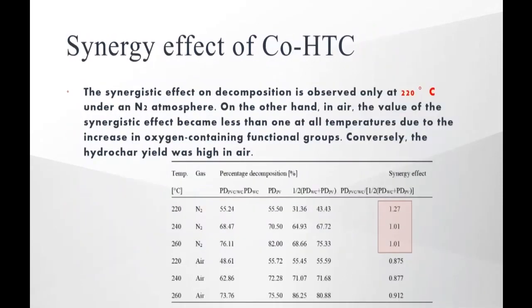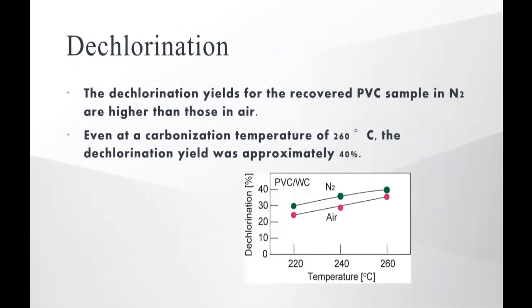We have summarized the result of the hydrothermal carbonization in this table. The synergistic effect on decomposition is observed only at 220 degrees C and a nitrogen atmosphere. On the other hand, in air, the value of the synergistic effect became less than 1 at all temperatures due to the increase in oxygen-containing functional groups. Conversely, the hydrochar yield was high in air.